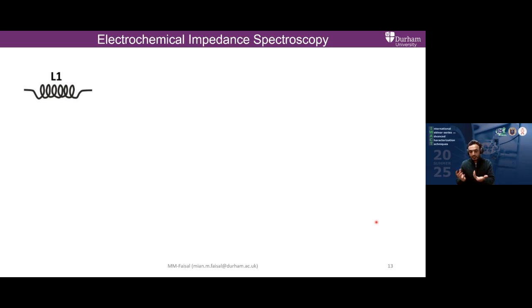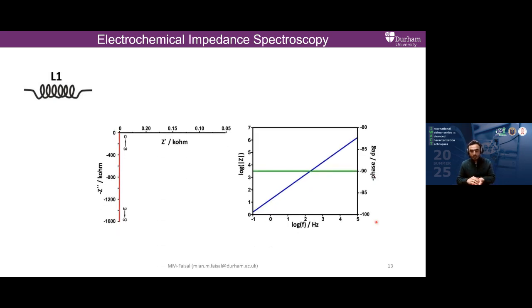But what if I use an inductor? An inductor is a passive device which stores energy in the form of a magnetic field, and there is a lagging between current and voltage in this material. So you will get zero resistance because it is not a resistive material, and you will get a straight line parallel to the y-axis in the Nyquist plot, which is presented here. This is the typical trend of an inductor if you connect it to the potentiostat and run an EIS measurement. In the Bode plot, you can see the phase is consistently 90, and that tells you that the potential is leading current by 90 degrees.